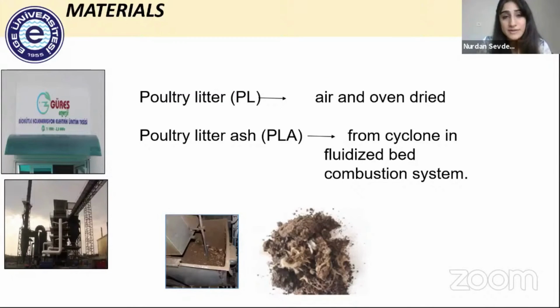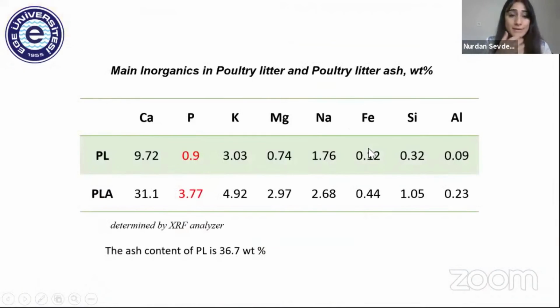The poultry litter was supplied by Güneş Company, first air dried and then oven dried at 150 degrees, and poultry litter ash was also supplied by Güneş Company. Here are the main inorganics in poultry litter and poultry litter ash. As seen, the poultry litter ash has a considerable amount of phosphorus. The huge amount of calcium in both is due to the animal's diet.